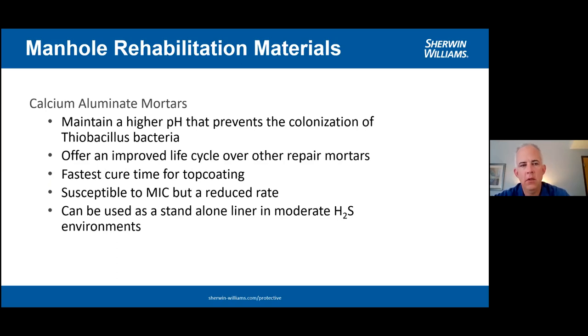If it's a very mild, very, very non-aggressive area of the collection system or the plant, we may do a calcium aluminate mortar as a standalone without having to put epoxy back over the top of it. Again, it maintains a very high pH that prevents the colonization of the thiobacillus bacteria, which, if you remember, is what excretes and causes that sulfuric acid accumulation. It offers an improved life cycle, much longer than standard Portland cement. It's very fast curing. It's susceptible to microbial-induced corrosion, but at a greatly reduced rate as opposed to what Portland cement is.